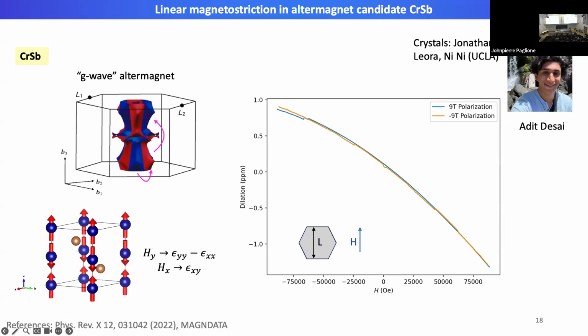So for this particular magnetic structure, there should be a few modes of piezomagnetic coupling within the ab plane, and those are the expected coupled magnetic field and strain that's written out explicitly. Right. So we set out to do this experiment with the dilatometer setup, where we have the length change and the magnetic field along the y direction in this notation here.